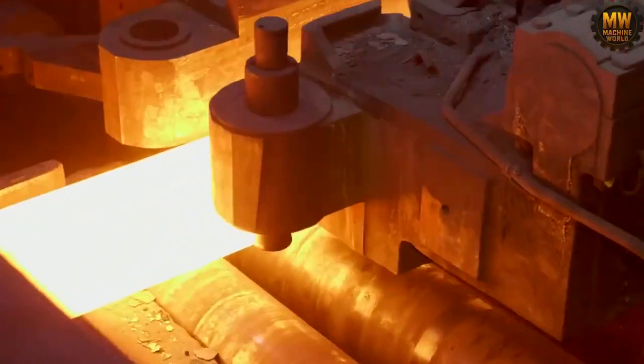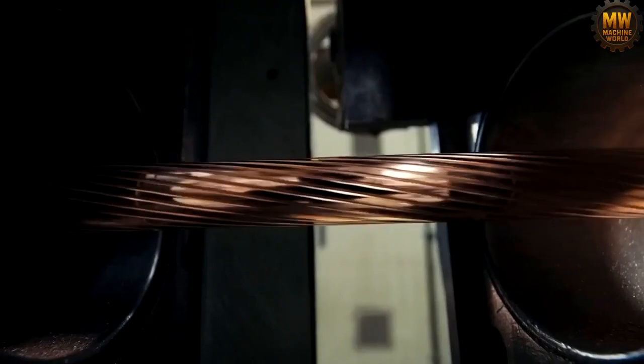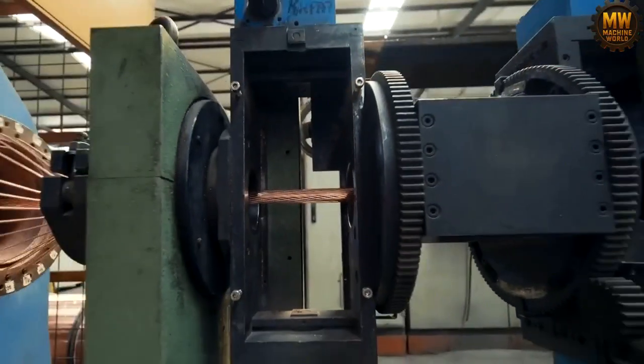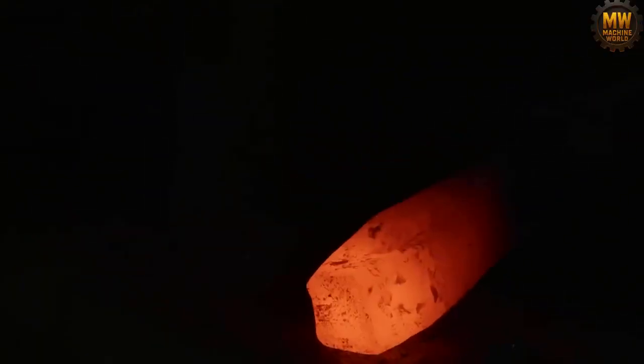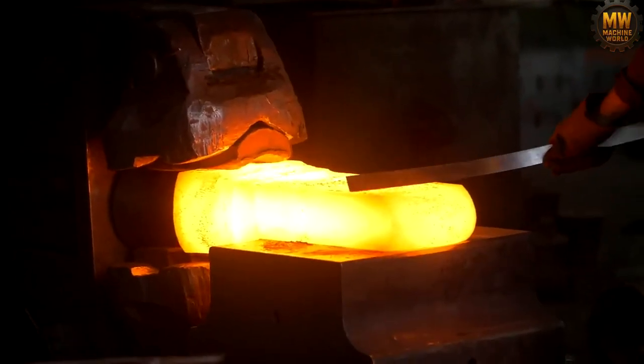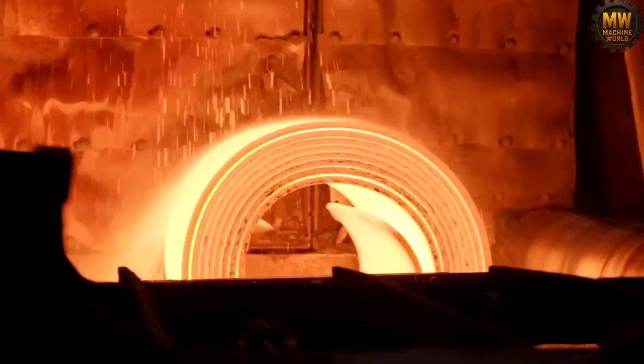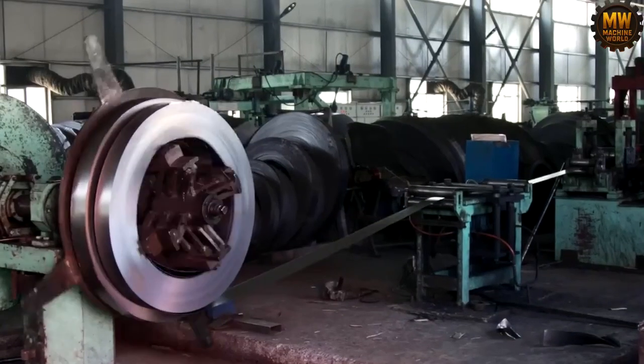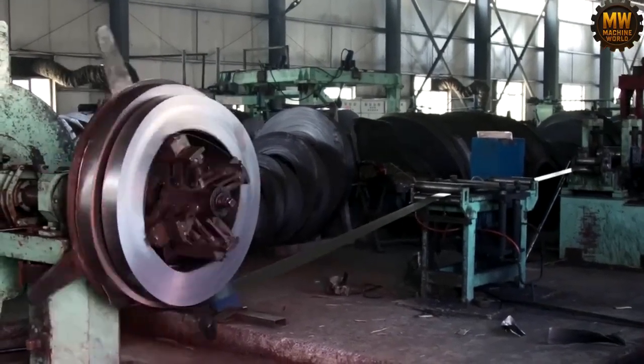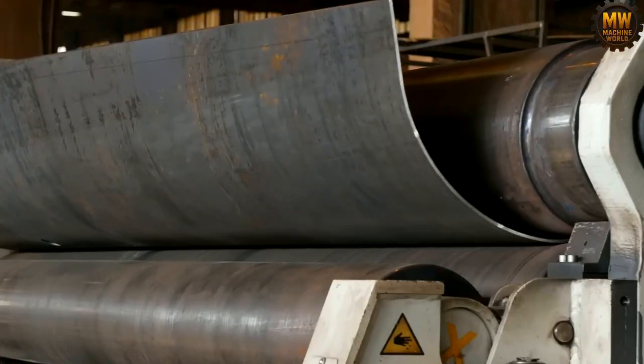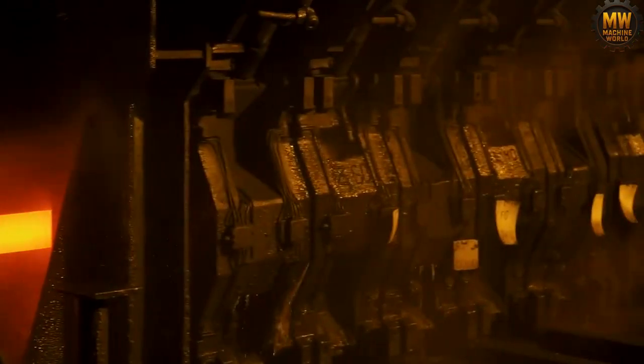The chaotic mountains of extracted ore have been purged and cast into flawless steel billets. Now, these dense monoliths face 1,000-ton mechanical profiling. Still radiating a pulsating orange glow, the metal enters the primary rolling mills at over 1,000 degrees Celsius. At this extreme heat, steel surrenders its rigid nature. It behaves like heavy, pliable dough. The blocks feed into a synchronized sequence of high-strength alloy rollers.